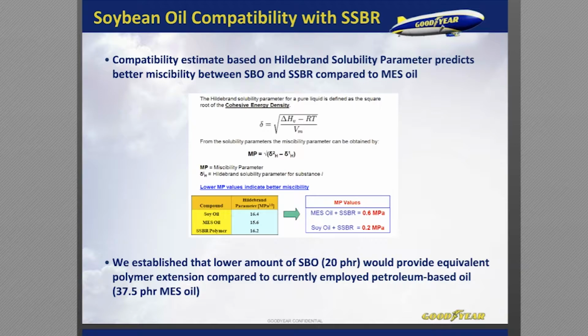Some of our early work was focused on looking at the compatibility of soybean oil with our tire polymers, specifically styrene butadiene rubbers, or SBRs. And the one thing that we realized right away was that it had better miscibility. Soybean oil was more miscible with SSBR than the current oil we were using. And this is big for us, whether it's as a polymer extender or as a free oil addition, is that we needed less soybean oil to provide the equivalent viscosity reduction, polymer extension, however you want to put it. But basically, we got to use less soybean oil on a part level than petroleum-based oil. That's big. It gives us a lot more flexibility in the design of our polymers and in the formulation of our compound recipes.